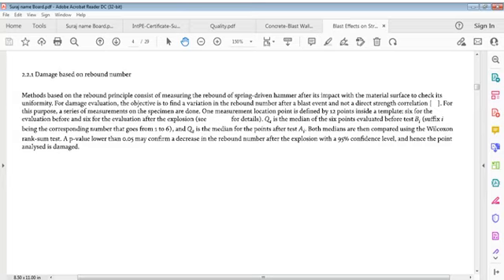Six points are for evaluation before and six for evaluation after the explosion. Q1 is the median for the six points evaluated before the test, being i being the corresponding number that goes from 1 to 6. Now Q2 is the median for the points after the test. Both medians are then compared using the Wilcoxon rank sum test. If the p-value is lower than 0.05, it may confirm a decrease in rebound number after the explosion with a 95% confidence level.